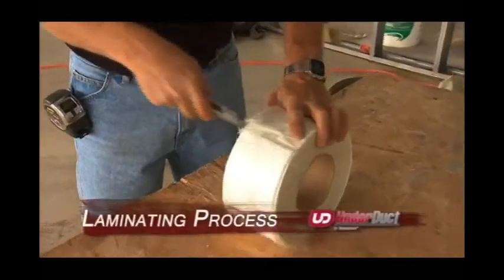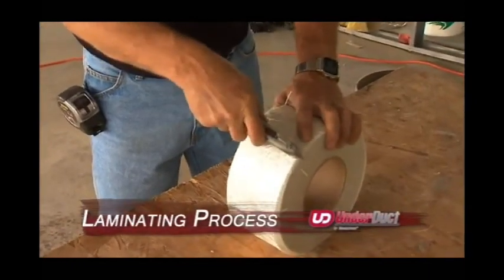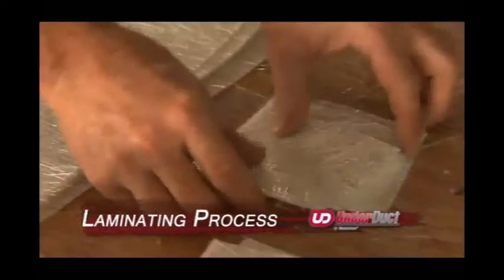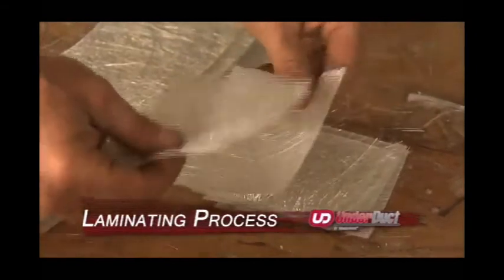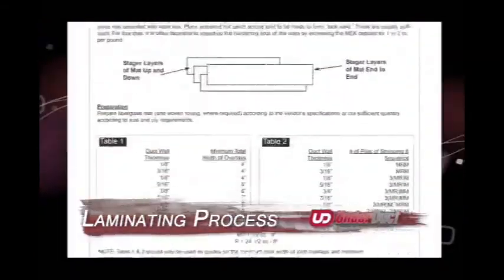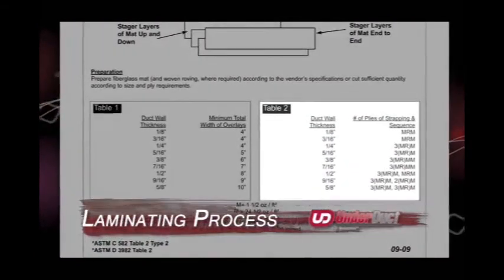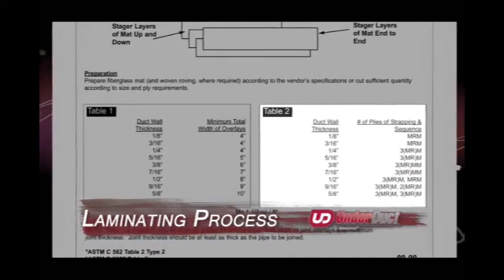Cut the glass mat strips in 18 to 24-inch laminating lengths. Also cut 6-inch long strips for hot patches. Review the written instructions for the number of layers for each size joint.